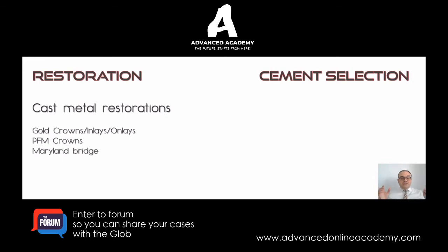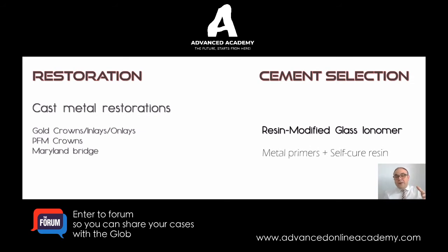If you are going to use a cast metal restoration, whether it's gold as an inlay, onlay, or a crown, you're going to use a resin modified glass ionomer if you have proper resistance and retention form. And if you want to bond it to the tooth, you're going to use a metal primer along with a self-curing, chemical cure resin. Okay, that's for cast metal restoration.